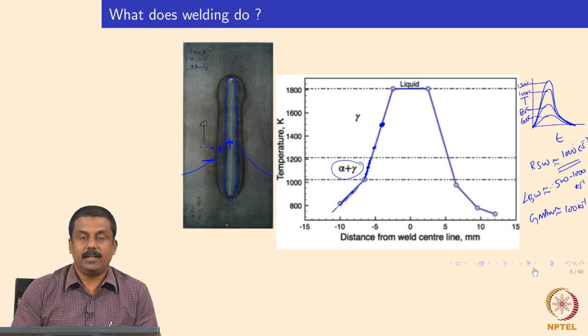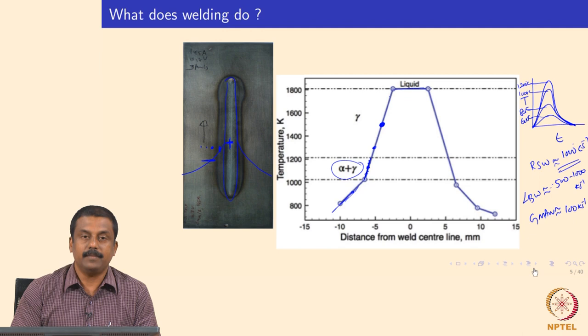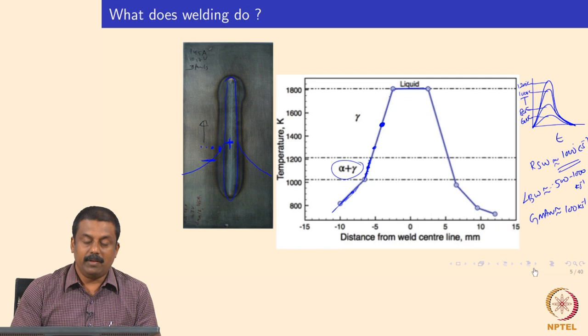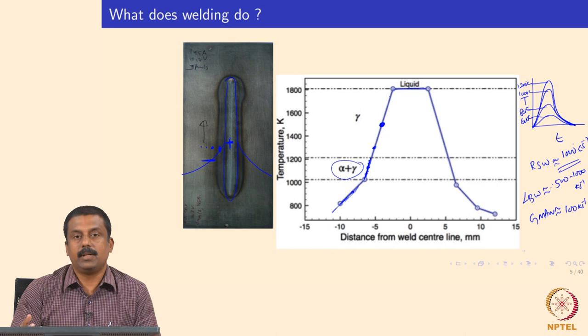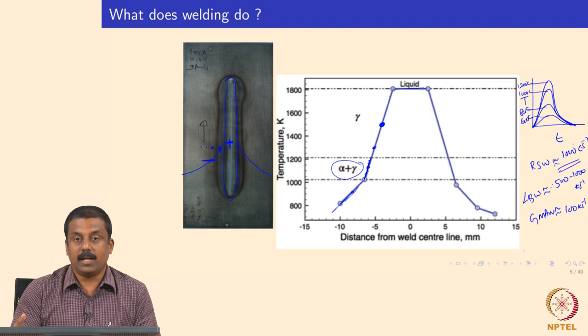When the temperature reaches the fully austenitic region, you have a fully austenitic microstructure with no benefit of carbon partitioning as seen at the intercritical annealing temperature. From this complex thermal cycle expected during welding, you may also expect a very complex microstructure generated after welding. Whatever carefully designed microstructure we have in the base material — generated from complex thermomechanical treatment and alloying elements — the weld has its own thermal cycle, and applying such a weld thermal cycle may result in a very heterogeneous microstructure.